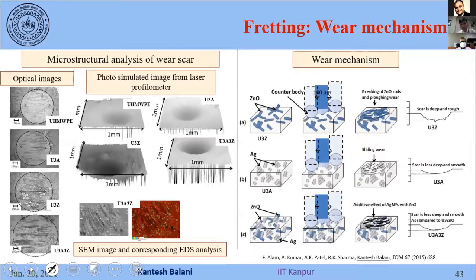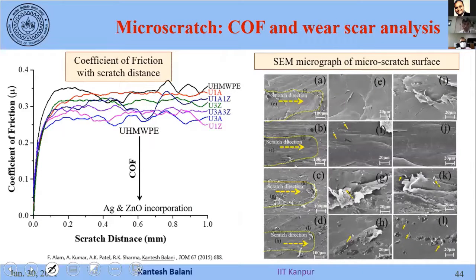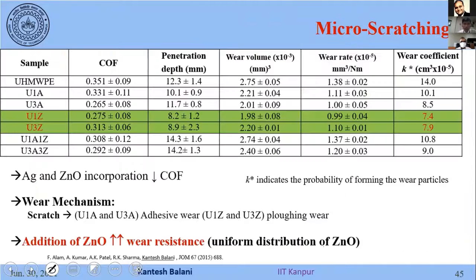Then we have done the elemental mapping, quantifying everything, but I will not get into that part. Now we go to micro scratching, and in micro scratching we've taken the scratch, and what do we observe here? The coefficient of friction is more or less similar, but I see that zinc oxide actually is helping here. First, I should say it is increasing the wear resistance, okay, that is fine, because the wear volume is the least.